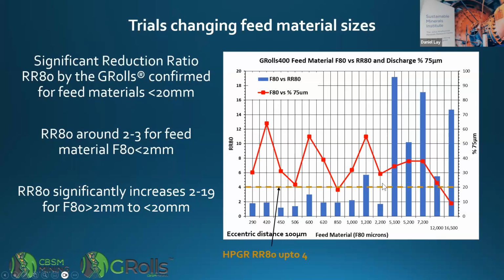A HPGR normally gets around about 4. Now, HPGRs normally don't operate in the minus. They don't normally receive feed less than 2 mil. They normally receive feed between 50 mil and 100 mil, so they're getting reduction ratios around about 4. So we're getting much higher reduction ratios, and that's because of the energy being used and the different shearing and crushing forces is much more